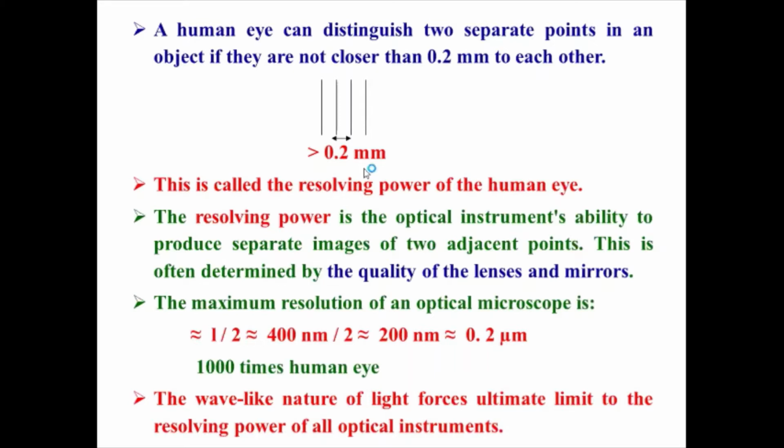So if you want to identify or look at anything with smaller dimensions, or objects spaced at a distance less than 200 nanometers, an optical microscope will not work. And in the 60s and 70s, there was a desire to see biological entities of smaller dimensions. So how can one get the images? Then electron microscopes were introduced. So why electron?